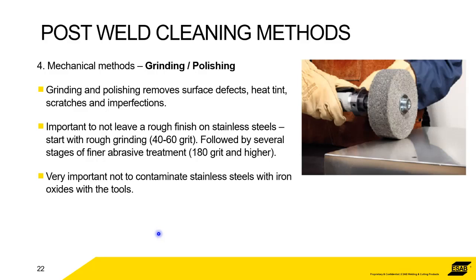We say gradually increase the grit number. So start off with a 40 to 60 when you're polishing, and then 180 and above, 360 even, to get a very high polish on there.